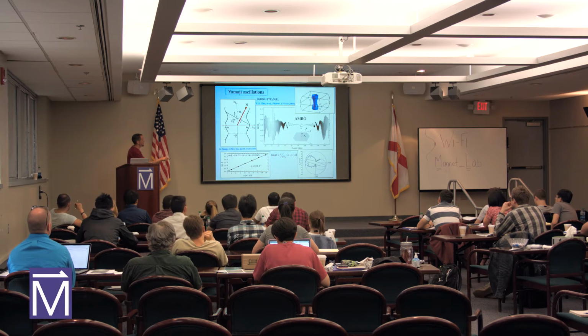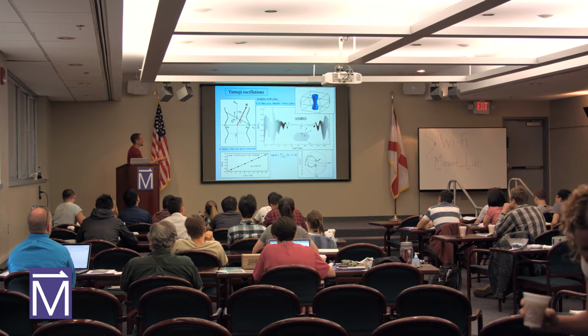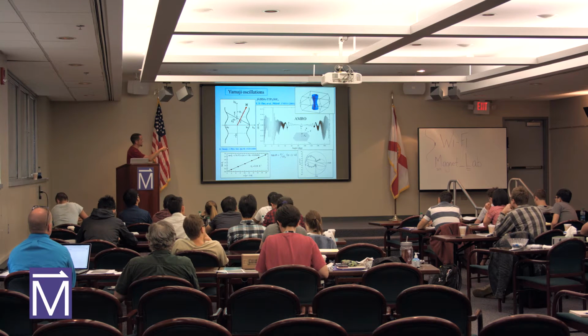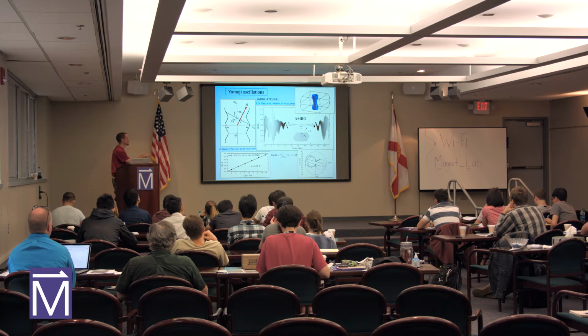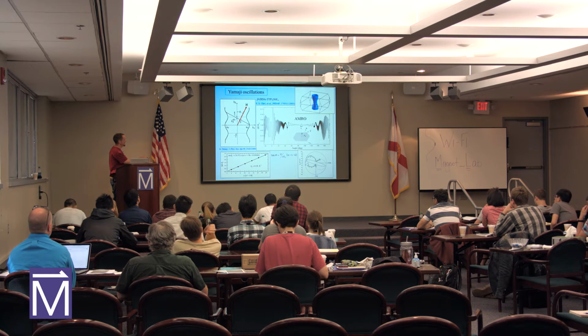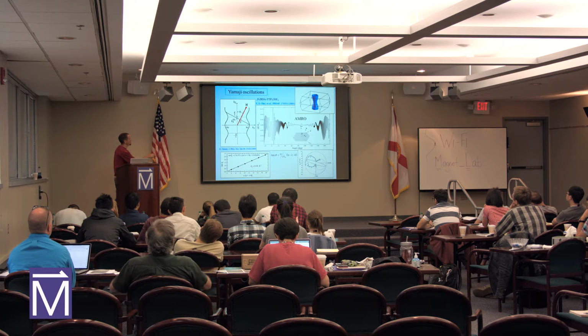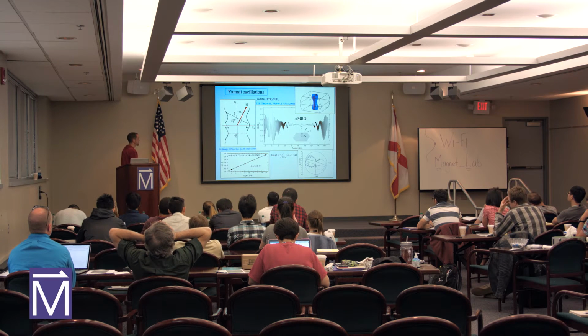If we go back to our picture of our quasi two-dimensional Fermi surface from the strontium iron phosphide, this just kind of shows the shape. If we took a slice of this, this would be the cross-section of that quasi two-dimensional Fermi surface. What they call this, when it has the skinny parts and the fatter parts, is that it has necks and it has bellies. Okay? If the field goes vertically through the screen along this kz axis, you'll get a different orbit frequency from the skinny part, the neck, and from the wider part, the belly. So that just gives you regular quantum oscillations that we've already been talking about.